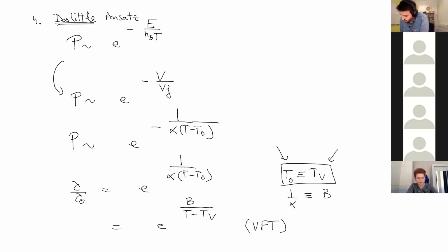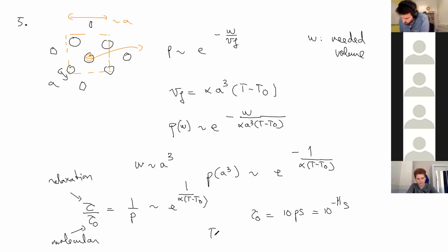And so this typically occurs. This is coming from experiments, but basically this is 100 degrees above really the divergence point, the effective divergence point. So if you put numbers, you have here the exponent. So let me take another blackboard. You have tau, which is tau naught exponential 1 over alpha (T minus T0). And when T is equal to Tc, the cooperative onset, then tau c is equal to